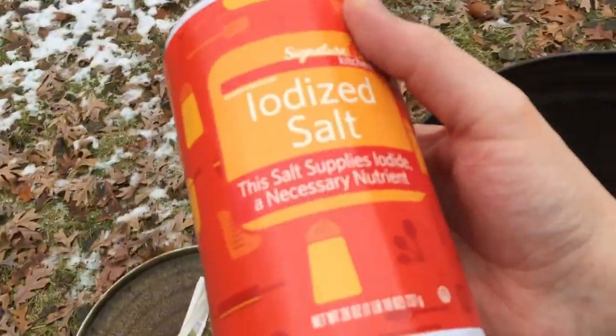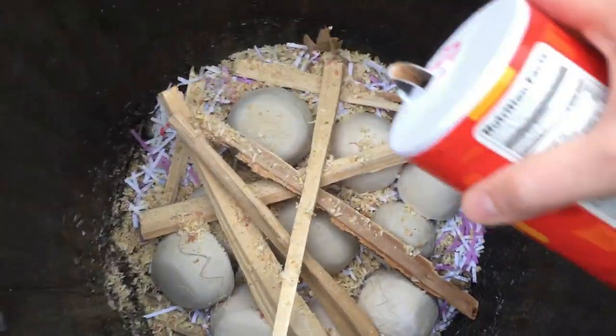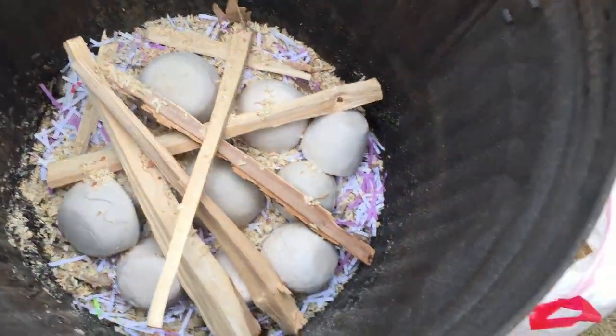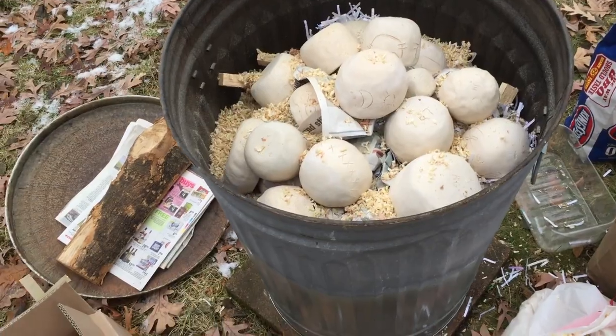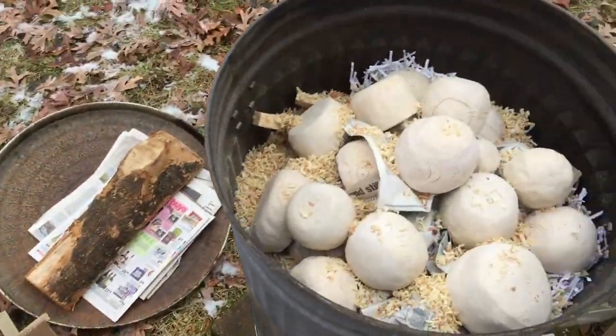The most unusual addition is a little bit of table salt. This tends to add little speckles and, if the kiln gets hot enough, can add yellows and reds to the pots — so fingers crossed. All the pots from all three boxes were successfully loaded in.